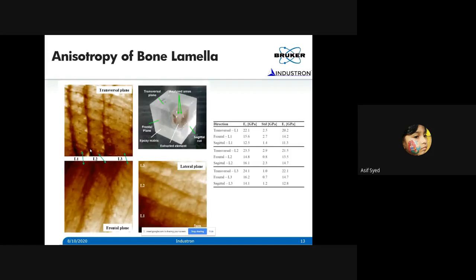For example, you can take a section of the bone, cut it, and polish it in three different directions. This is the transverse direction, this is the frontal plane, and this is the lateral plane. So you can make measurements in all three of these directions. Like I mentioned, with the scanning probe microscope, on each side you can do an SPM image. This is the 5 micron length scale.